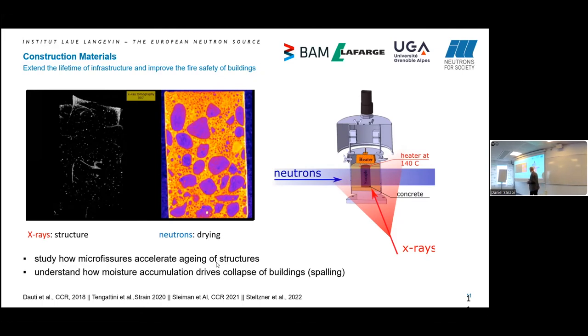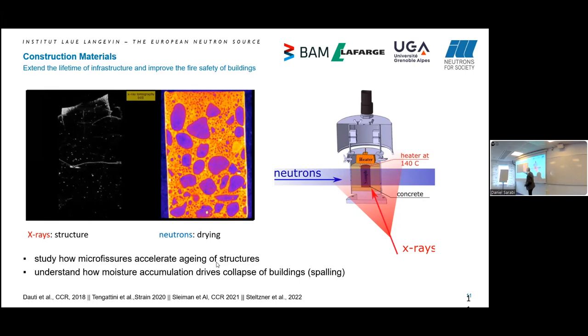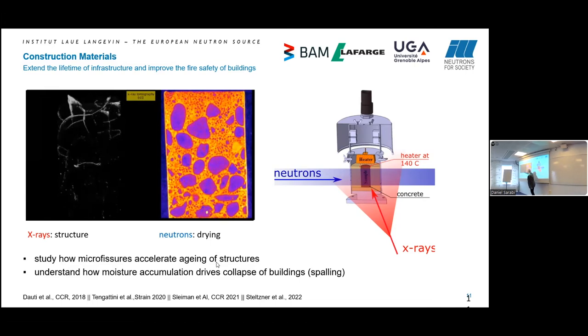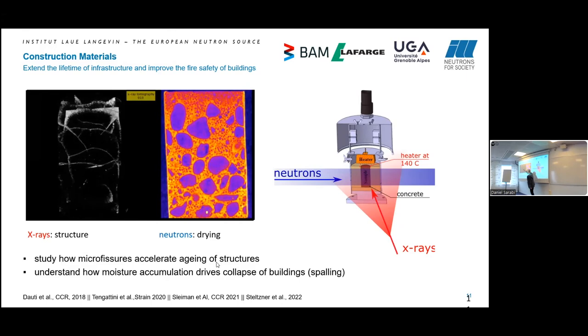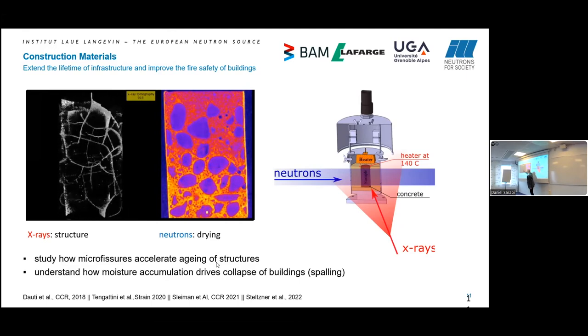But anyway, in this example, we collected X-ray tomographic data to look at the development of fissures in the concrete, and used neutrons to look at how moisture traveled within the concrete as it was being dried. So neutrons can distinguish between the grains and different parts of the cement that have different moisture contents, which X-rays can find much more difficult. The X-rays are really good for looking at fissures in concrete.